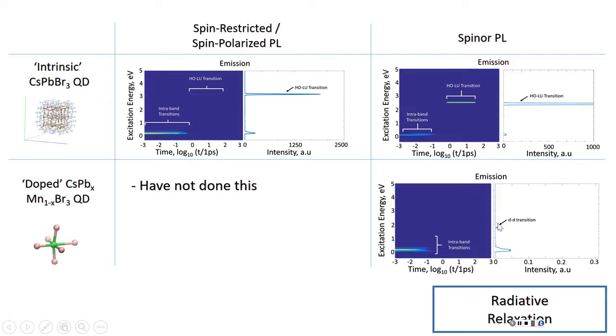The doping constant, well, for one dot, it's pretty small. Small, but still probably not a single manganese. Yeah, that's true. But even if you had 100 manganese, each of them will contribute these D levels. Of course, they might be split due to the interaction between these impurities, and this will increase your intensity. So that could account for maybe one order of magnitude.